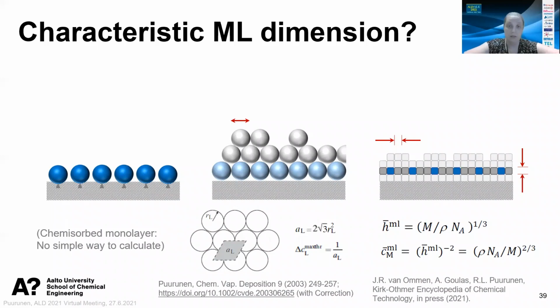For physisorption, there is. If you know a radius of this molecule, then you can easily calculate how much you can fit in a hexagonal close packing, and then you get the maximum theoretical amount absorbed. And for a solid, you can always take an average monolayer by considering the density and the molecular mass and calculating from that.